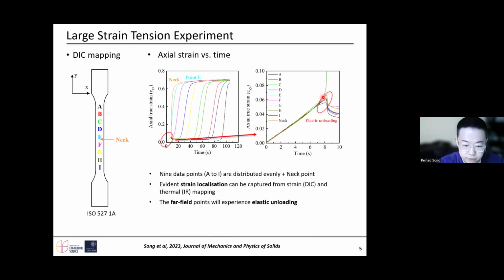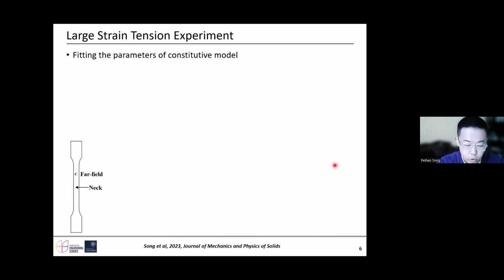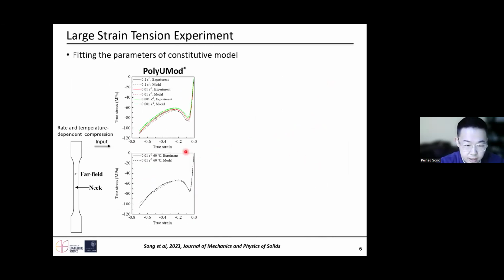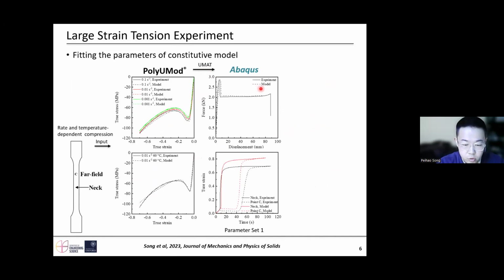And the rest of this data point, the far field point, will experience elastic unloading. So how we understand this strain localization and elastic unloading, I built up a FE model. I use the rate and temperature dependent compression data as an input because the compression deformation is quite homogeneous. And then I put that data to this software, generated a UMAT. I put that UMAT in FE simulation software.